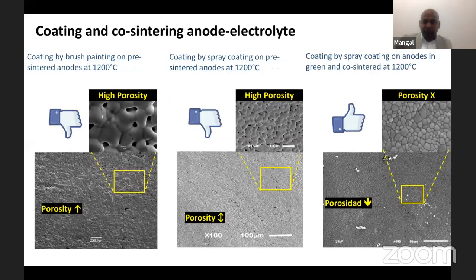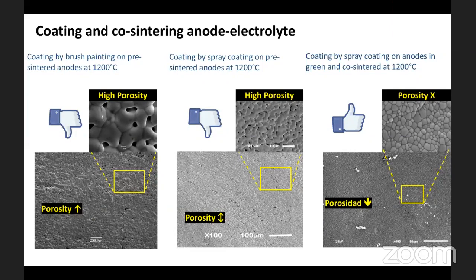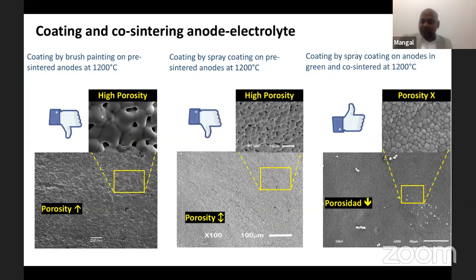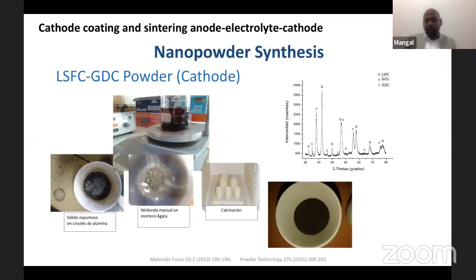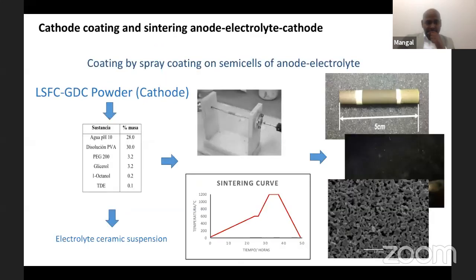So with many trials, finally we achieved a highly dense electrolyte coating, and that was sintered at 1200 degrees centigrade. The anode sintering and later the electrolyte coating over the anode were sintered together, and then we need a cathode coating. For that we obviously need cathode powder. For the cathode powder also, we prepared composite powders based on lanthanum strontium cobalt ferrite and gadolinium doped ceria. We used a similar coating technique and similar slurry formulation, and over the electrolyte we coated the cathode. You can see on the right hand side the length of the tube is 5 centimeters.